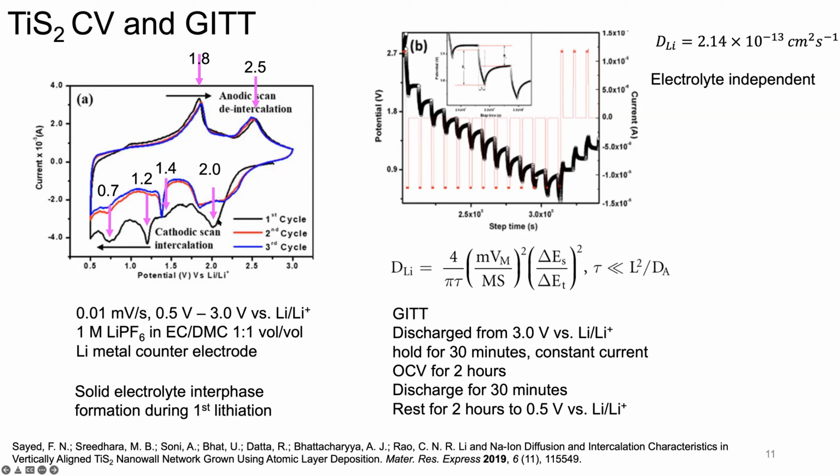And what we see that's quite peculiar, even though this is potentially a single phase solid solution material upon lithiation, what is peculiar, and this is seen quite often in sulfides, so this is something to look out for, is that the first lithiation scan is quite different than that of the delithiation, or the cathodic versus the anodic scan. And you could see that already in the displacement of the voltage. So upon reduction and oxidation mechanism.